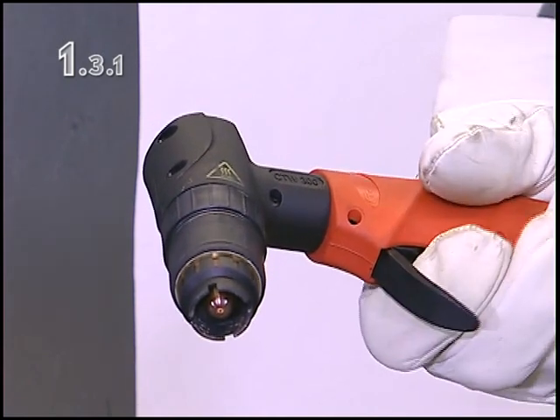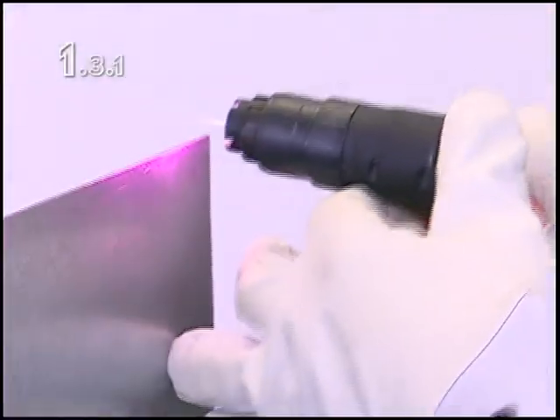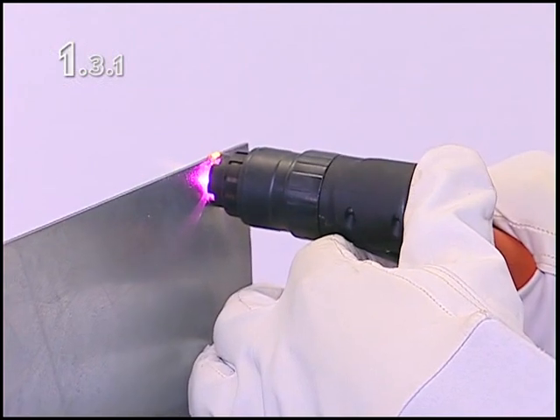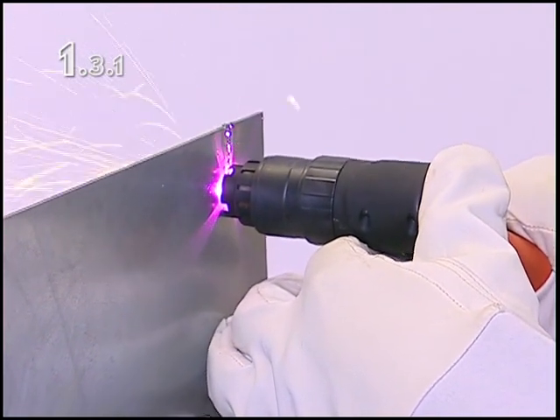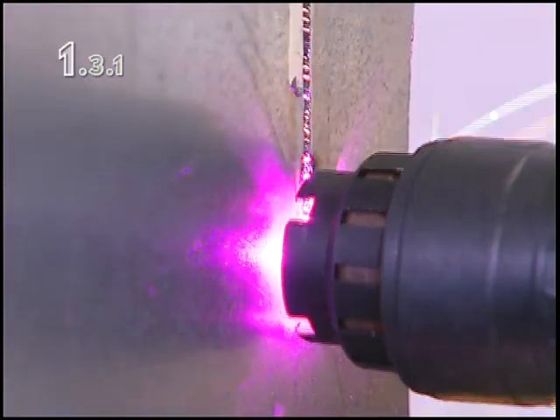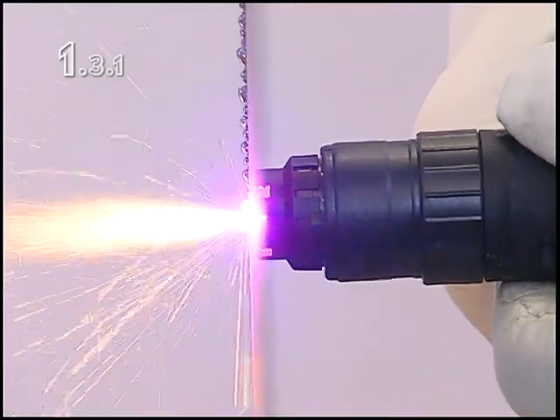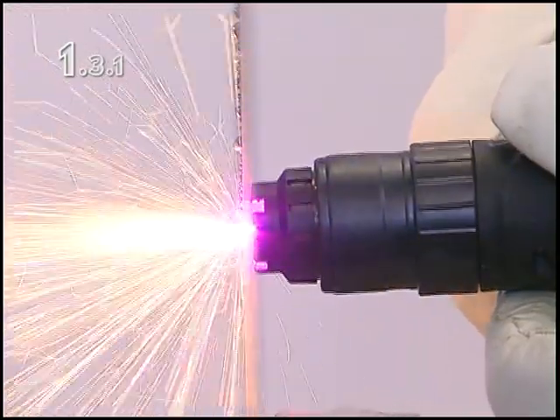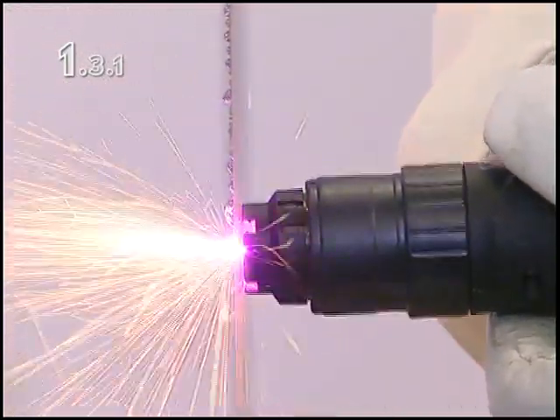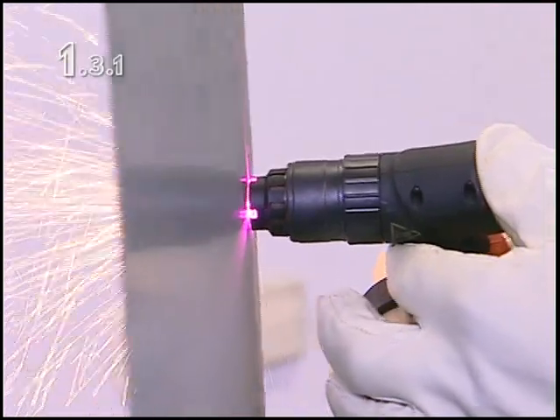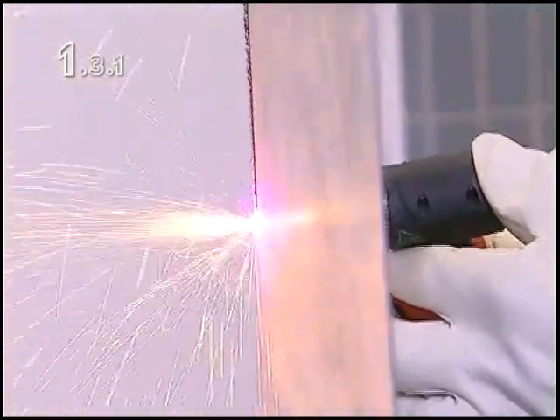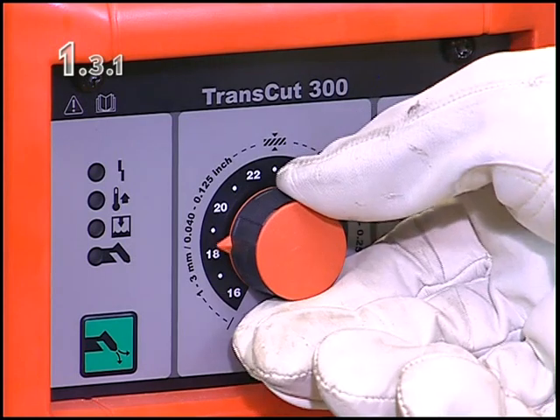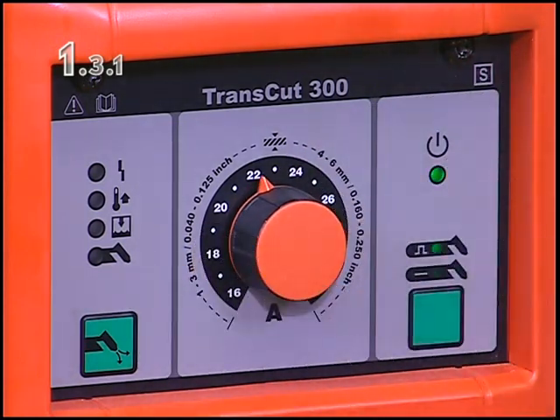When pressing the torch switch, hold the cutting torch away from face and body. If possible, move the cutting torch over the workpiece in a pulling motion. While cutting, make sure that the arc penetrates the workpiece and that there is as little dross formation as possible. If this is not the case, the cutting current should be increased or the cutting speed reduced accordingly.